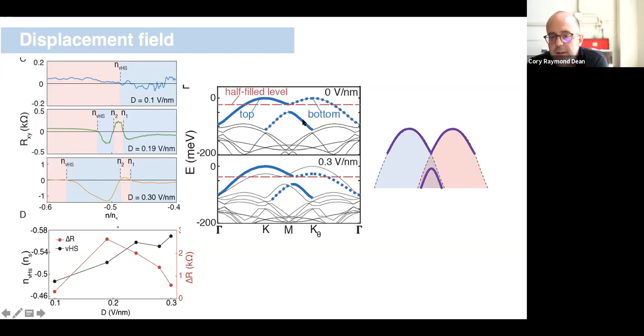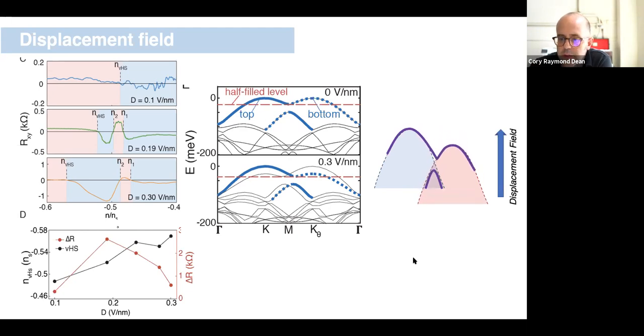And then if I apply a displacement field, the relative energy positions of the two layer bands change as a function of displacement field. So in my cartoon image, what happens as I apply a displacement field is I just shift one layer band relative to the other layer band. The really nice consequence of that is that I'm effectively changing the bandwidth of this isolated flat band. The other thing that happens as a consequence is we shift the position of the Van Hove singularity. This is, again, all calculated assuming a single particle picture.